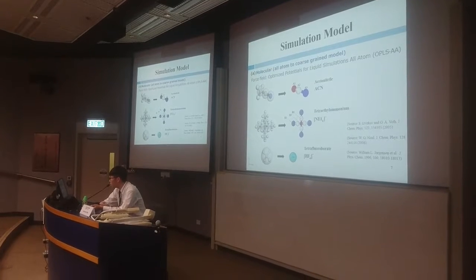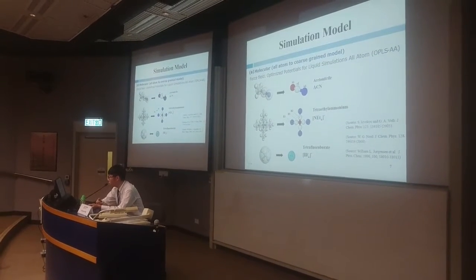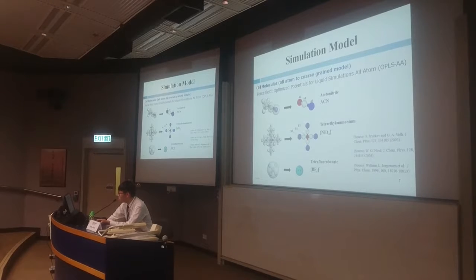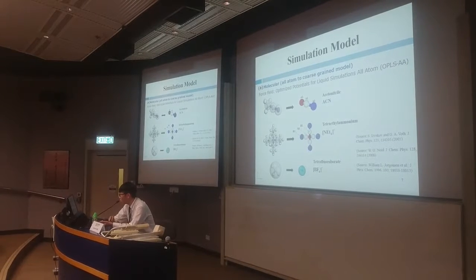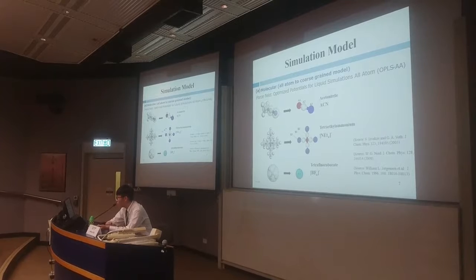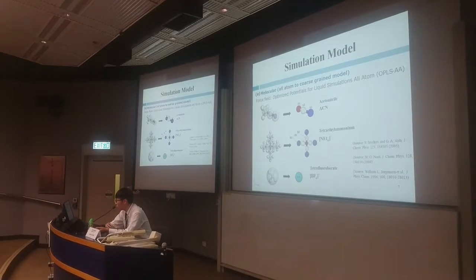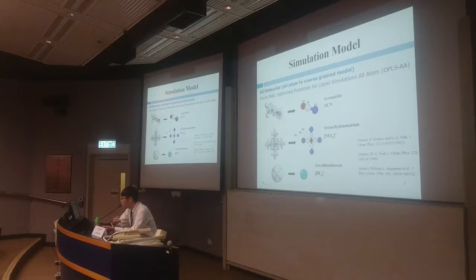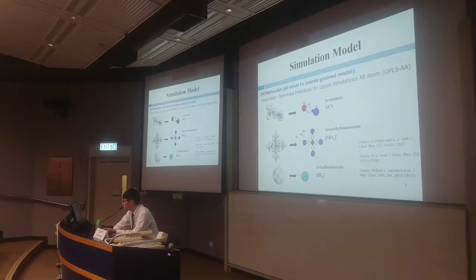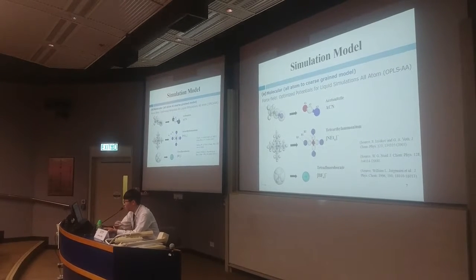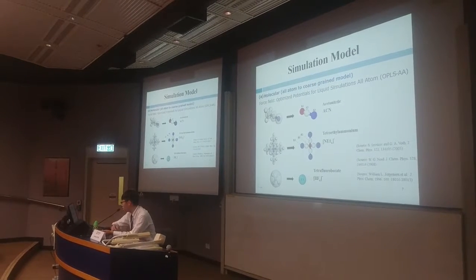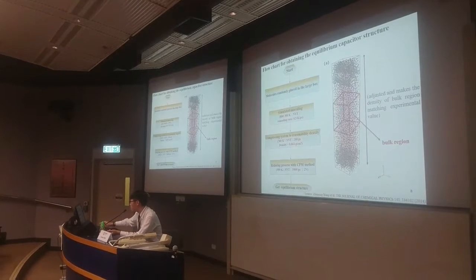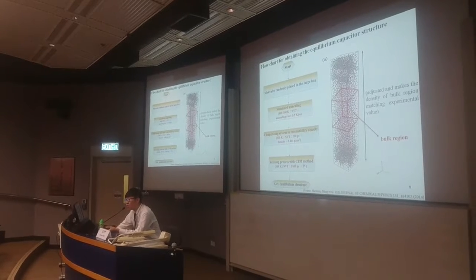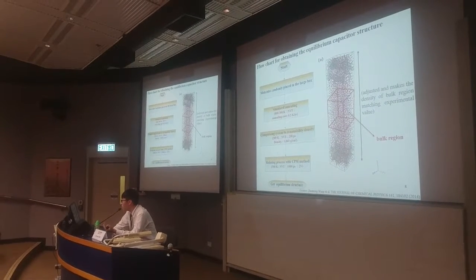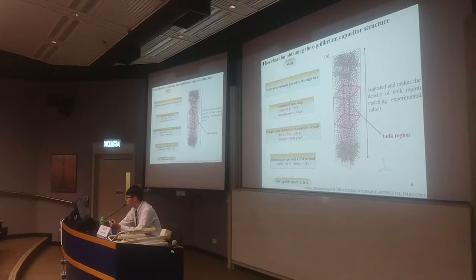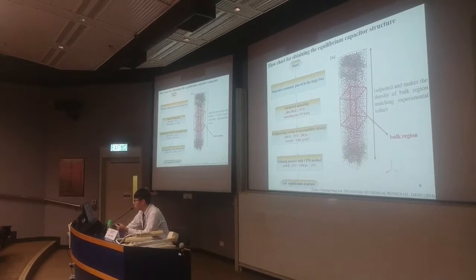revert to the multi-scale coarse-graining method, which was developed by the group, which is used to derive a coarse-grained force field for the molecular liquid from the atomistic scale forces. And we get the CG parameters through this method. So after we obtain the CG parameters, we follow this procedure to get the EDLC model.